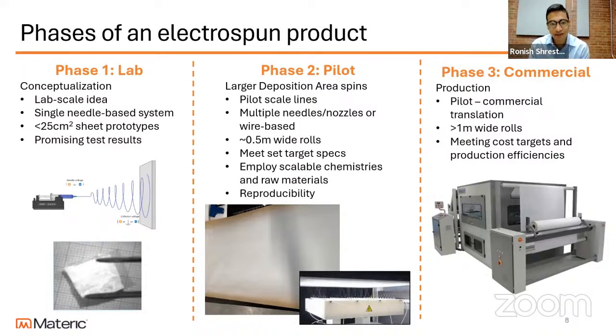And that's where we come in at phase 2 and phase 3, where we're working firstly with the pilot phase, phase 2, where now instead of using a single needle, we're using a larger number of needles or nozzles or a wire-based system and depositing onto larger areas. Here we have both our systems, which are 0.5 meter wide rolls. So we can make 0.5 meter wide rolls that are hundreds of meters in length. When we're doing these optimizations, we also focus heavily on using scalable chemicals.